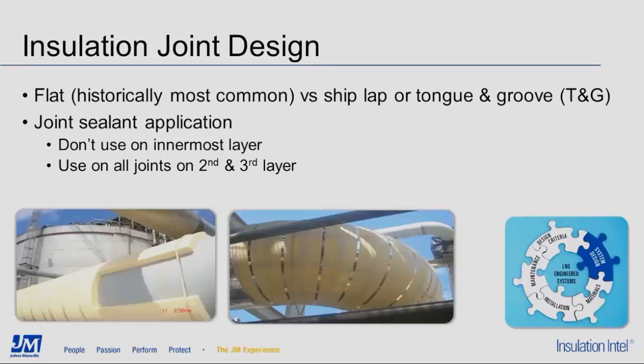This allows the innermost layer, which sees the greatest temperature change from installation to operating temperature, to best accommodate any expansion or contraction that occurs. In the left picture, you can see that there is no joint sealant being applied to the innermost layer, while the right picture shows the use of joint sealant on the second layer. Where joint sealant is used, it should be applied, as I said, as a thin layer across the entire joint face. That's a key design attribute.